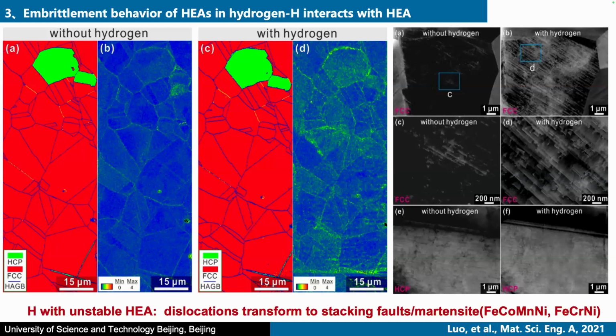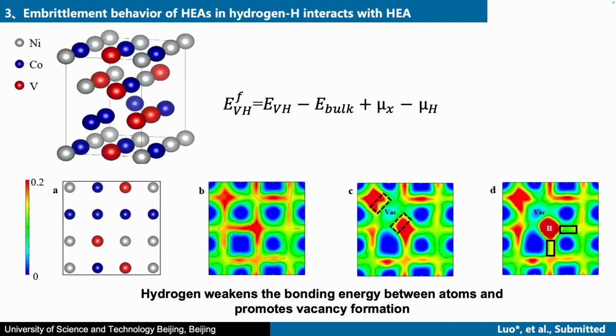normally, take this for example, it contains two phases, FCC plus HCP. If we charge it with hydrogen and observe in a similar experiment, we found that in the FCC phase, the dislocations can transform to martensite of very small size. But in the HCP phase, the dislocation density only slightly increases, so it is different. Come to the next step.